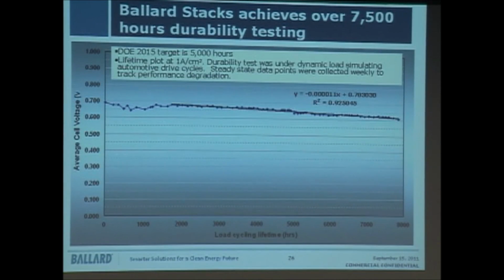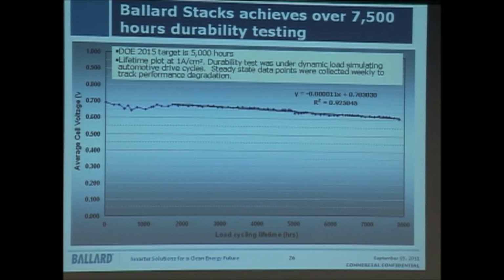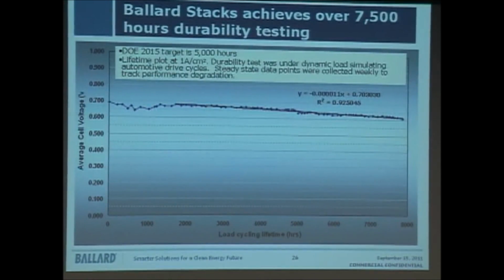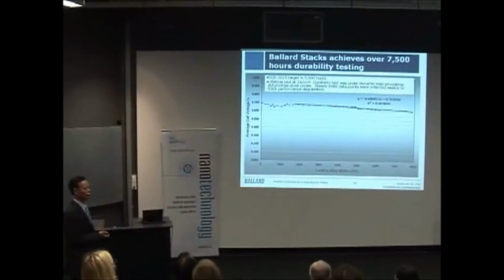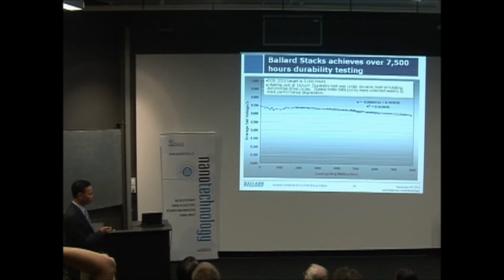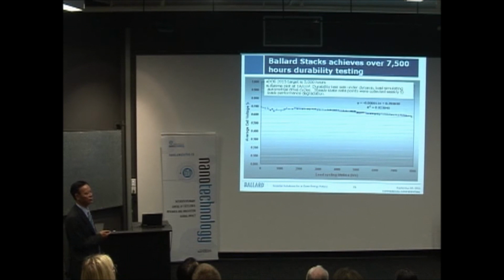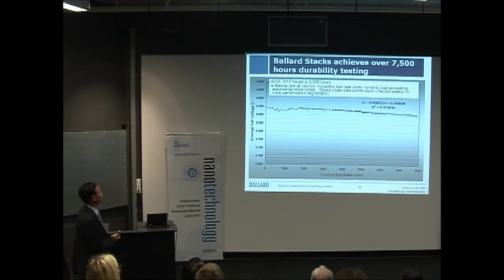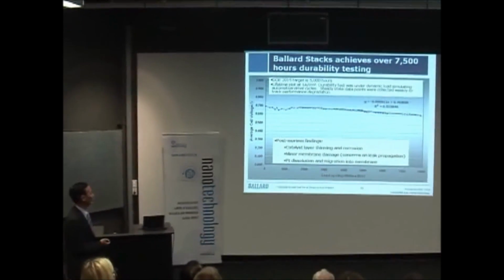At Ballard, we also demonstrated in 2007 that we can achieve 5,000 hours of operation. That's equal to 105,000 miles equivalent. So we get no more than 5% performance degradation within these 5,000 hours. But this is at 1 amp per square centimeter, the real-world needed power, not like those mass activity tests only based on 0.9 volt. So we do have the opportunity to get the durability we wanted. However, that is based on relatively higher platinum loading, not something we want as a DOE 2015 goal. So that's the reason why we think we need more work on that.